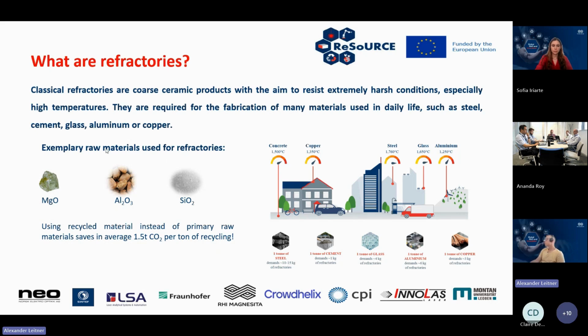For that, we use three main raw materials, I would say. The first one is MgO with a high melting point of roughly 2800 degrees C. Then for lower melting point applications, we also have alumina, which is close to 2000 degrees C, and then silica more in the range of 1500 degrees C. And what I've mentioned before: if we use recycling instead of primary raw materials, that gives us an enormous benefit in terms of CO2 savings. For every ton of recycling used, we can save roughly 1.5 tons of CO2 in our production.